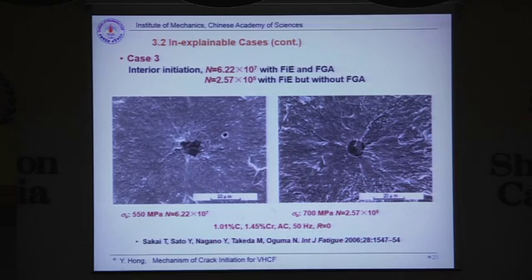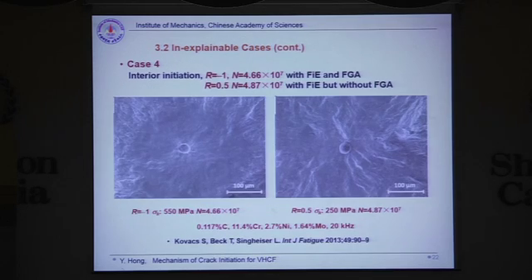The third one is very interesting. For the case of loading after 60 million loading cycles, there is an FGA morphology, but for the case of a relatively small number of loading cycles, there is no FGA morphology. And the fourth one shows that for a stress ratio of -1, there is a morphology of fisheye and FGA.